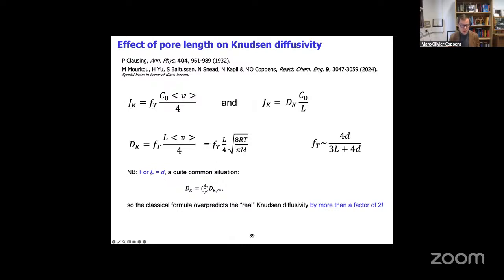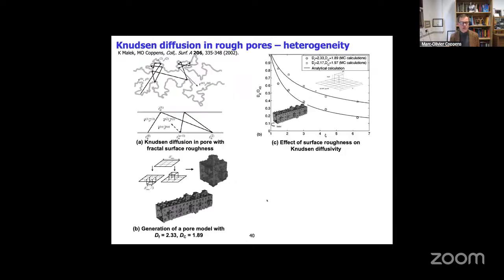And so just to show you what effect this is, if the length of your pore would be the same as the local pore diameter for a cylindrical channel, then you're over-predicting the real Knudsen diffusivity by more than a factor of 2. And yet, this is the type of model that's often used even in pore network models. So one has to be very, very careful. So even on simple pores, cylindrical pores, be careful what model you use for the Knudsen diffusivity.